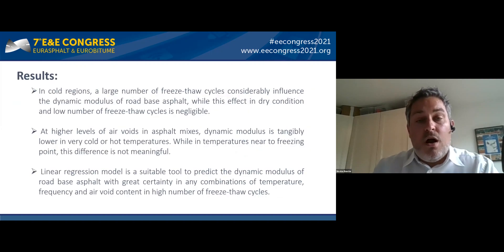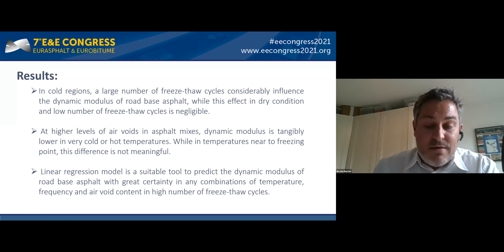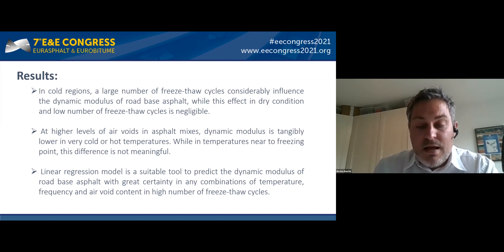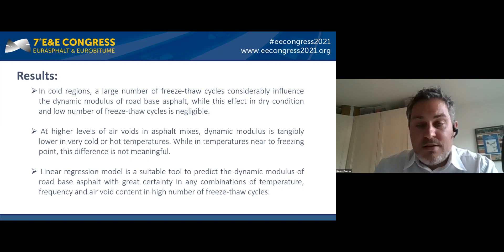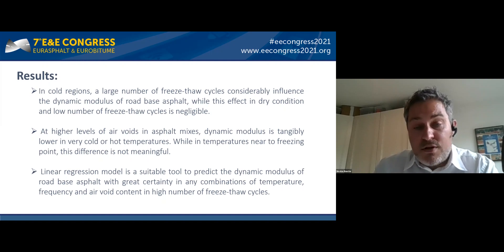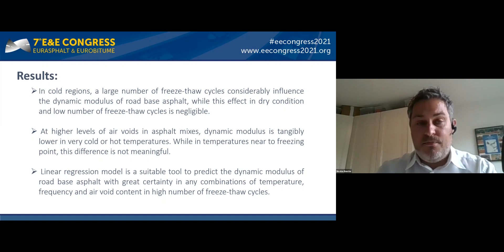In conclusion: in cold regions, a large number of freeze-thaw cycles considerably influences the dynamic modulus of road base asphalt, while its effect in dry conditions and with a low number of freeze-thaw cycles is negligible. At high air void levels, dynamic modulus is tangibly lower in very cold or hot temperatures. The linear regression model is a suitable tool to predict the dynamic modulus of road base asphalt with great certainty in any combination of temperature, frequency, and air void content after a high number of freeze-thaw cycles. Thank you.